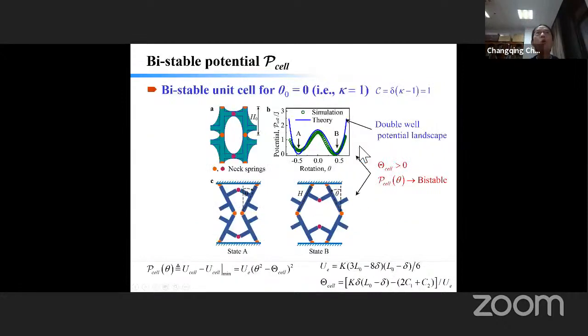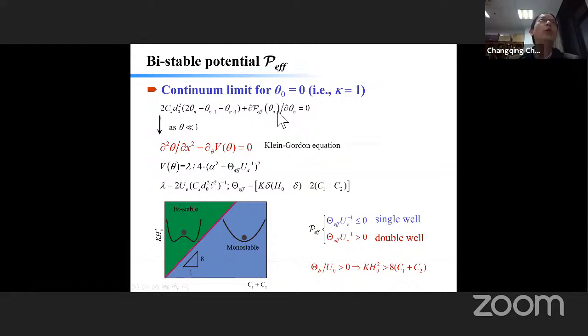Now we can consider another case, theta 0 equal to 0 and kappa equal to 1. Sorry, theta 0 equals 0 and kappa equals 1. Now, for this particular case, we calculate P cell. Now, we are able to get the potential, which you can see has two minima. So it's a double-well potential. And for this particular case, the structure is bistable. Again, for this equation, in general, we are not able to get an exact solution because it's very complicated.